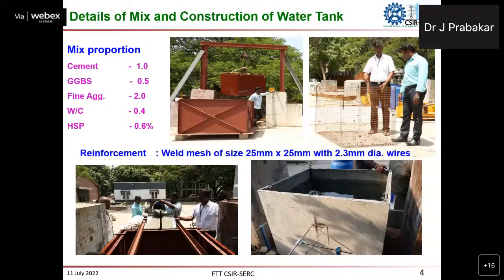For that, we have developed a mix with this cement composite: one part cement and fly ash, or you can go with GGBS. About 50% of the material is used both as a supplementary material as well as a filler. We used fine aggregate, and we also used a viscosity modifying agent, so that the consistency and uniformity of the mix are not disturbed.